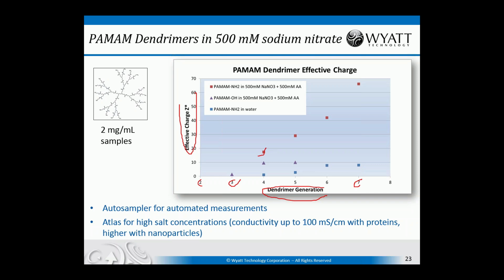They're very robust. And despite the very high salt concentrations, we can measure proteins and small nanoparticles in solutions with conductivity of up to 100 millisiemens per centimeter, which is very high sensitivity. Of course, you can measure much larger particles easily, even if the salt concentration is high. When you have very large particles, that's not so much of a problem. They scatter a lot of light. You have robust signals. The problem is when you have proteins, and we can make measurements on proteins of just a few mg/mL with these very high conductivities, which is quite unique.